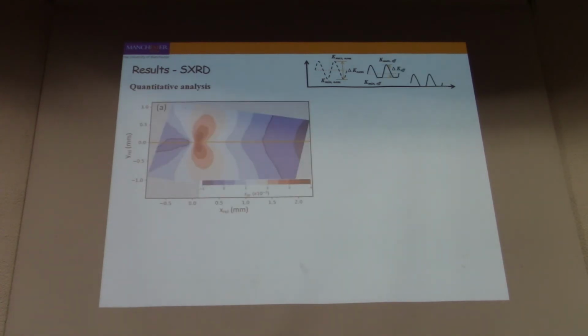So we observe the decrease in the stress, but if we want to know exactly how much the stress or the stress intensity factor is reduced, we can do the fitting. I used Williams' approach to fit the strain field in the crack opening direction.